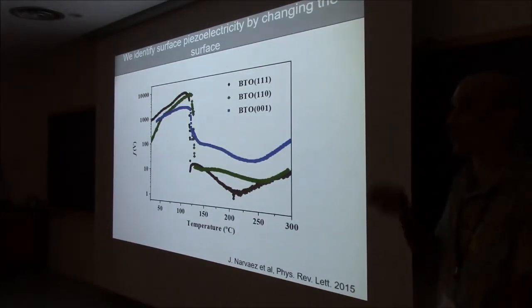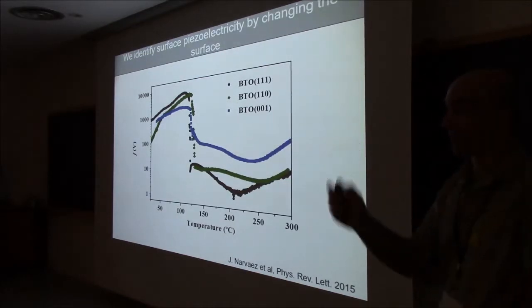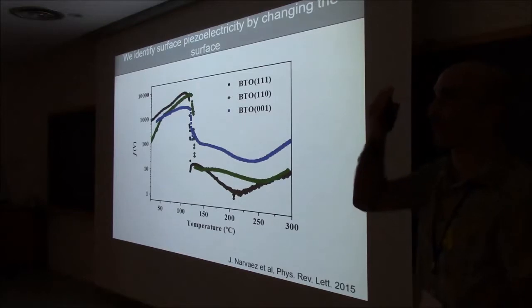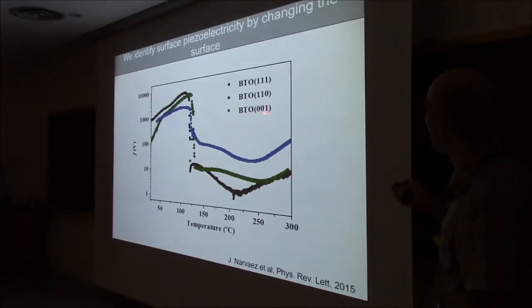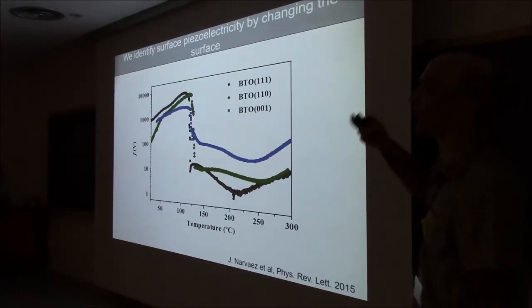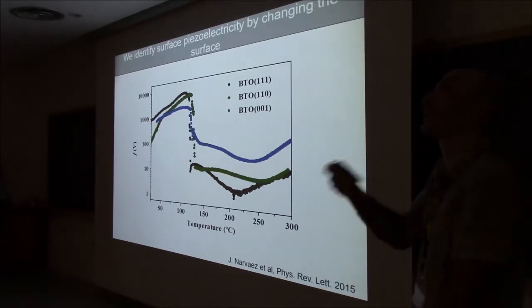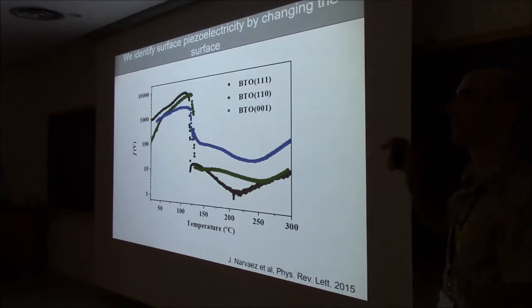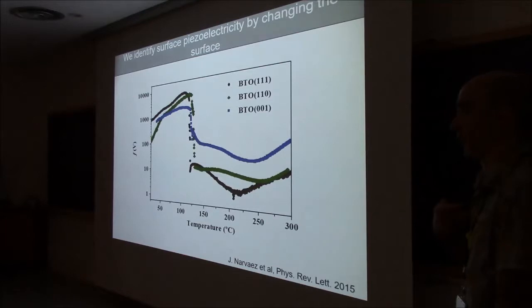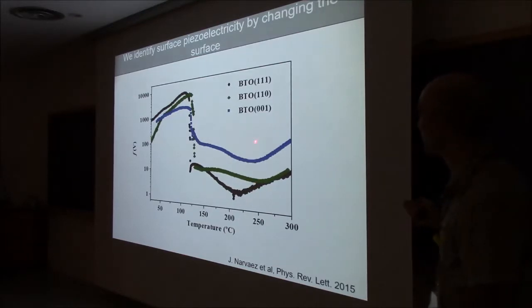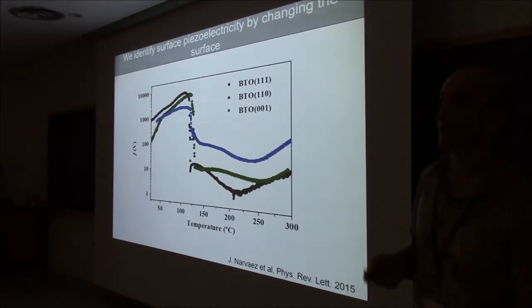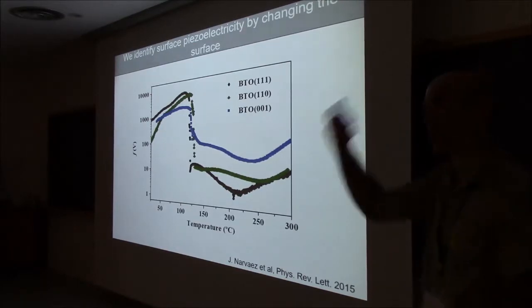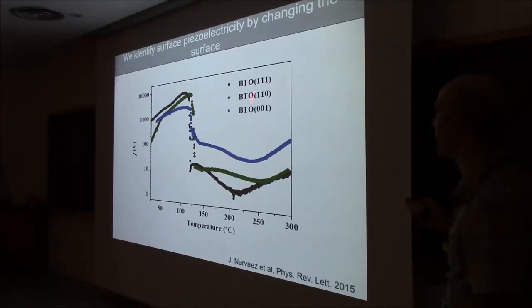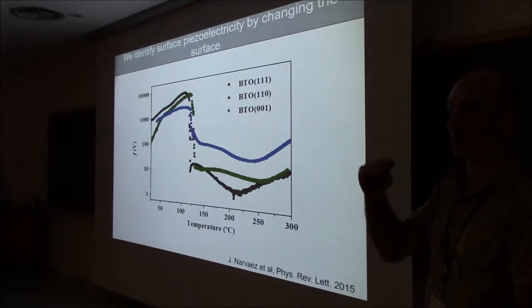Now, if the flexoelectric tensor was the same as the dielectric constant, which is a two-rank tensor, this would be perfectly isotropic, which means that these three things should be exactly identical. But it's not a two-rank tensor; it's a four-rank tensor, which means that it has no reason to be perfectly isotropic. But you can quantify what is the maximum difference. Someone can, not me. Max Engel can, and he did. And the maximum difference that you should get between these three orientations is a good bit smaller than what we've measured, a lot smaller. But yeah, that's a good question. So, a priori, even though it's cubic, there's no reason to expect that the three orientations will have exactly the same flexoelectric coefficient. Good point.